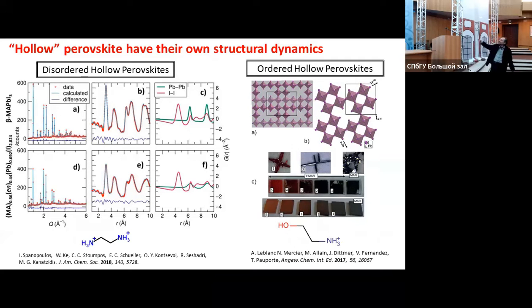And this model clearly shows up if we use this +1 cation, we just change this part. The charge matches now, and you can clearly see the crystal structure forming holes with missing octahedra. So these are the ordered hollow perovskites. This is work by Nicolas Mercier at Angers in France.